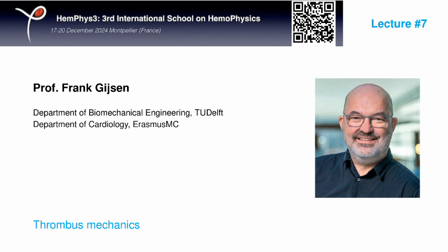So the hysteresis effect that we observe will always be a combination of a poroelastic effect and a viscoelastic effect. And teasing them apart, I think we need models to do so. Otherwise, we will be just juggling around with these numbers without knowing what to look at. So at this point, I cannot answer that question because we didn't do that yet.